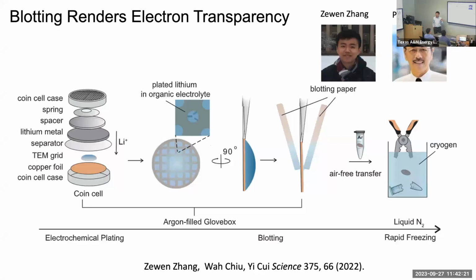Not only that, last year we had this paper. We figured out how to freeze the batteries while the organic electrolyte is still in there. But you need to do it in a way that the organic electrolyte is very thin, otherwise it's too thick and the electron beam cannot go through. So we developed this blotting paper technique, learning from biologists, to generate a very thin film of liquid and then plunge freeze it in liquid nitrogen.